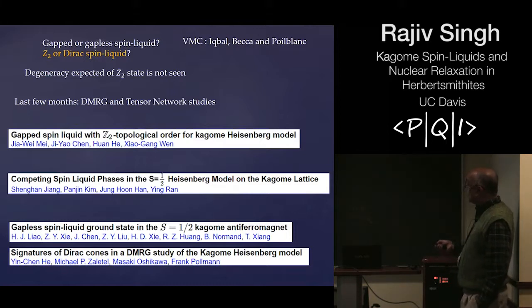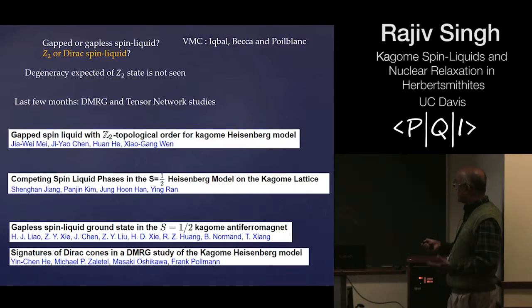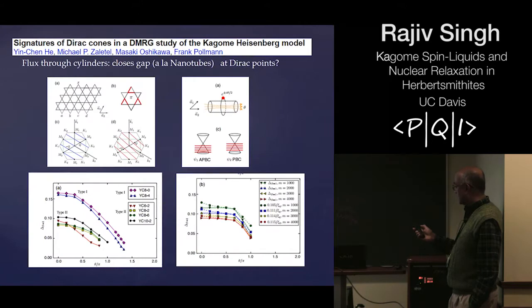So there are a number of papers just within the last year, the last 6 months actually. First of all, there is this variational calculation by Iqbal, Becca and Poilblanc, which argued that it is actually a gapless spin liquid. But these papers, first of all, DMRG, although people have argued for this gapped Z2 spin liquid, they have not seen certain topological degeneracies that are known to exist in such a Z2 spin liquid in the numerical studies. And this work by Xiao-Gang Wen and collaborators using tensor network methods argued for a Z2 spin liquid. This was more mixed about Z2 versus Dirac spin liquid, but these two papers very strongly favor a gapless Dirac spin liquid. So let me just very briefly mention this last one because it introduces some new ideas really.